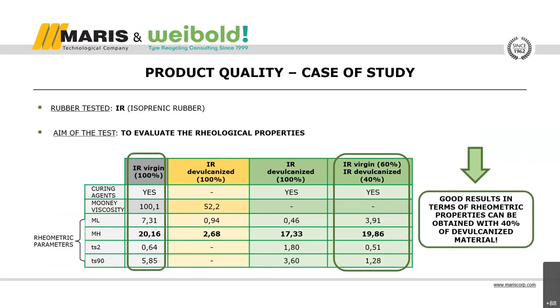The next analysis I would like to show you is the evaluation of the rheological properties performed with an ODR rheometer. ODR means oscillating disc rheometer. Without entering into the details of the analysis, in brief, the rheometer measures a degree of cure over time at a given temperature. The plot reports a measure of a torque value over time. The main parameters are shown in the tables below.